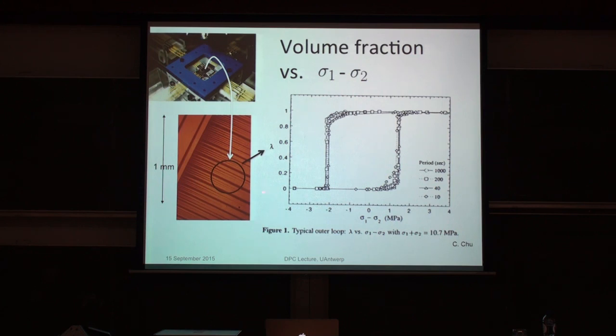It's not important. But then this graph was obtained by taking this window and digitizing it and finding the area fraction, which turns out to be the volume fraction because these interfaces are perpendicular to the specimen, and making this graph. Then you see different dots corresponding to different measurements, and on this graph are represented dots in which a certain loading program was done in stress space, but the period was changed. This was changed by two orders of magnitude from 1,000 seconds to 10 seconds, and you can see that you get the same loop, okay? That's so-called rate-independent hysteresis, and that's a very typical kind of hysteresis in phase transformations.